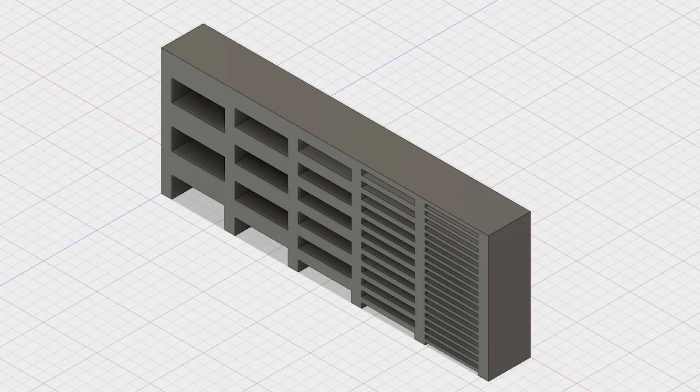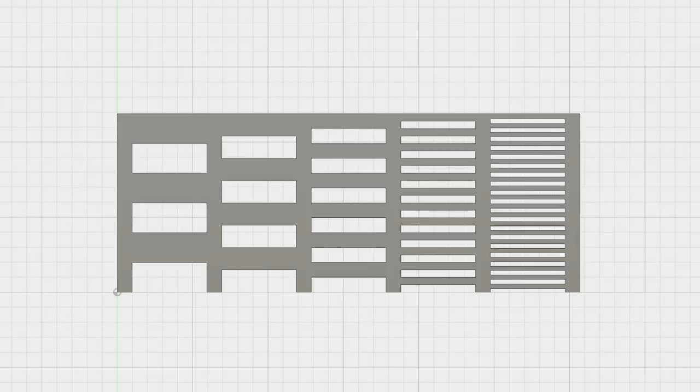For models with small negative features, too much light energy can be a problem. If we dial in the exposure, the 500 micron and larger gaps are clearly resolved. The 250 micron gaps are partially resolved,